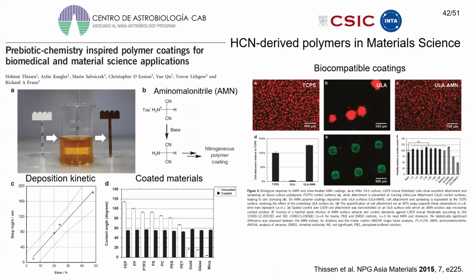Thus, by immersing the item to be coated directly into a water solution containing the trimer of hydrogen cyanide, aminomalononitrile, after several hours at room temperature, the item turns dark. This method is effective for coating various materials, and the thickness of the coatings depends on the reaction time. This author has demonstrated the biocompatibility of the aminomalononitrile based films using multiple tests and methods.